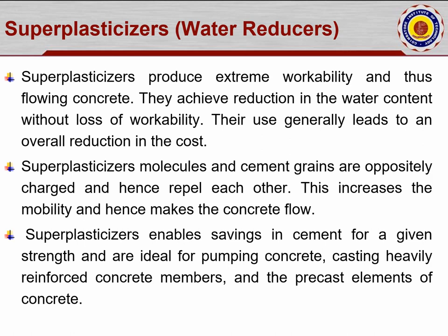In heavily reinforced members — such as bridge elements with many rods in a given area — super plasticizer plays a major role in increasing the strength and workability of the concrete. In precast stages also, super plasticizer saves cement content: for example, M30 grade concrete with super plasticizer added may reach the strength of 40 N/mm², reducing overall cost and saving cement content.